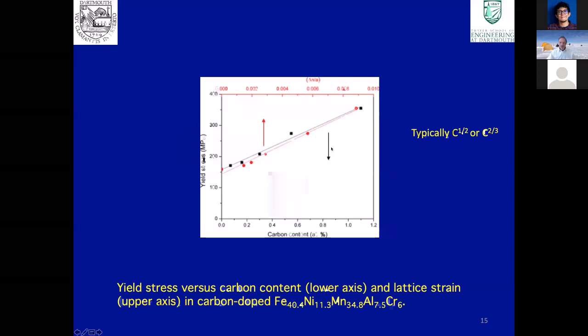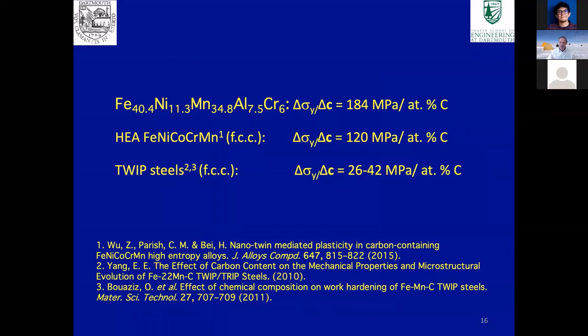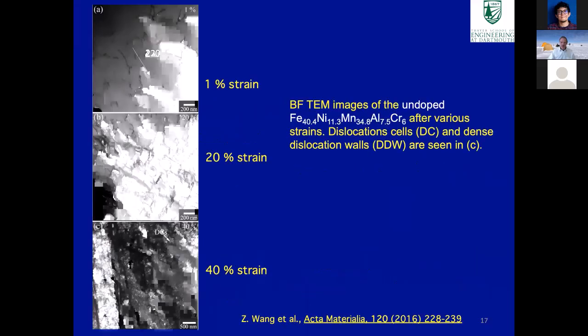You can plot the yield strength as a function of carbon. Sorry about the fuzziness of this image. You can see we've got a pretty much linear relationship here, which is unusual because typically when you have solute strengthening, you've got a concentration to the 1/2 or concentration to the 2/3 relationship. If you look at the strengthening we get from carbon, it's about 184 MPa per atomic percent carbon, which compares pretty well looking at other materials. This is another common high-entropy alloy, and this is a steel. And you can see that the strengthening effect is greater for this material.